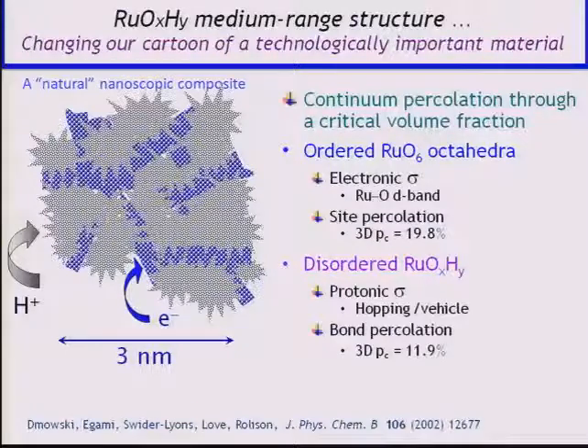So this system behaves chemically completely different relative to these dehydrated crystalline forms. These can be dissolved in HF. You have to go to a sodium flux with this very hydrous disordered form, and you've got bulk proton conductivity. So we did some atomic pair distribution function analysis of the structure in collaboration with Takeshi Egami then at Penn and Wojciech Dmowski, his senior staff scientist. And what came out is that regardless of how much water is in the hydrous ruthenium, down to 2 moles of water per RuO2, there is always a true rutile crystalline core. But it's only 1 or 2 nanometers, which is why you don't see it by X-ray diffraction.